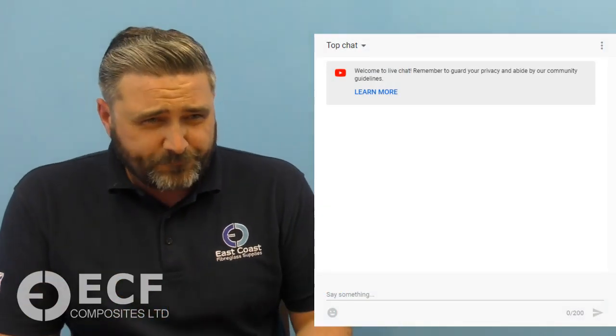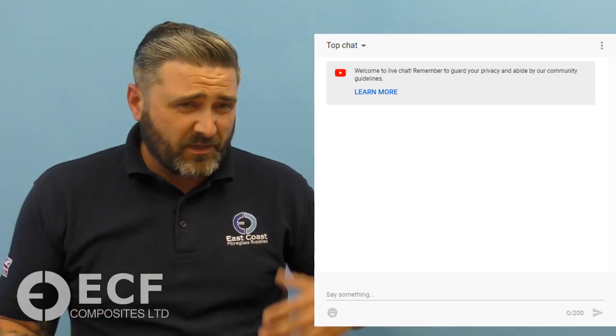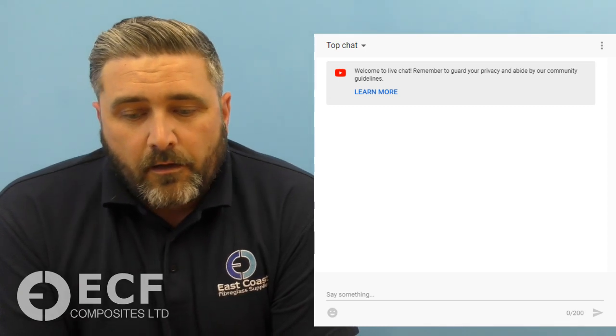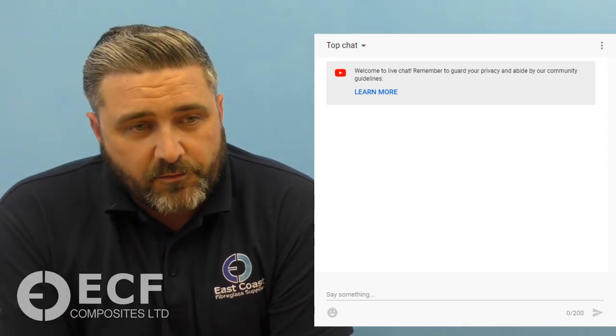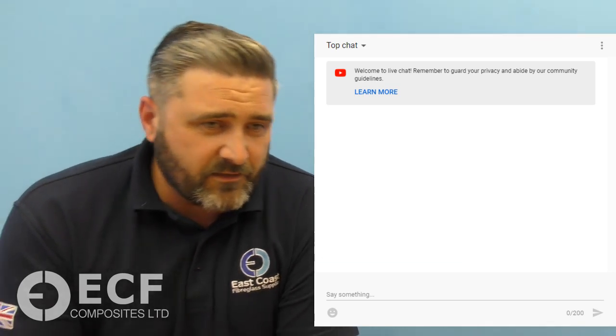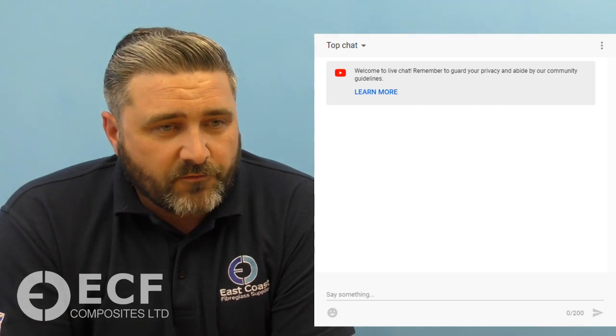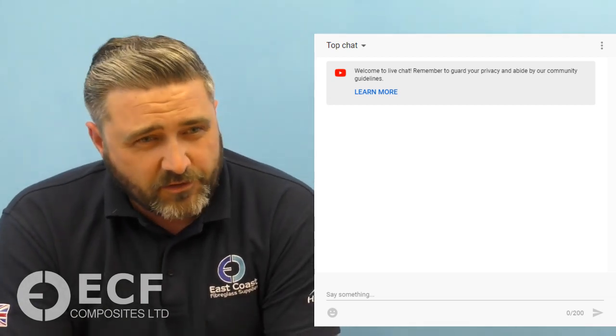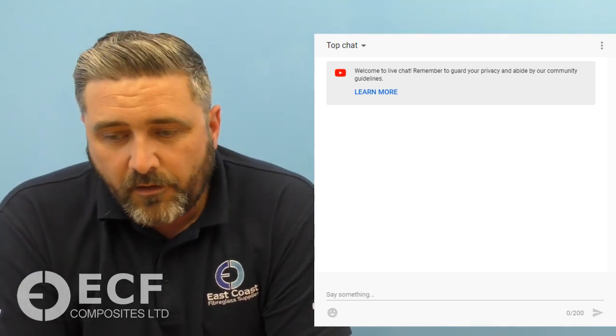Gel coat, for those who don't already know, is for putting into a mould. It comes in various colours. We have a massive range of RAL colours there. So that goes into your mould first. You let it cure off to a tack finish. A good test is just to run your finger across it to make sure no colour comes off your finger, but it is tacky to the touch, and that's an indication of a good time to start laying it up. And then you put your fiberglass on.